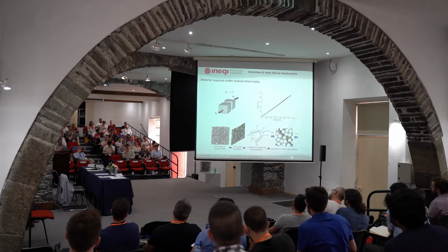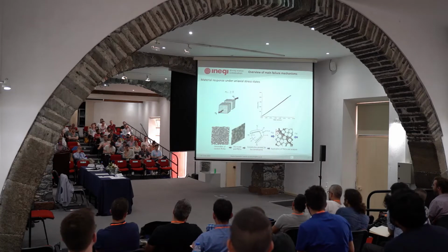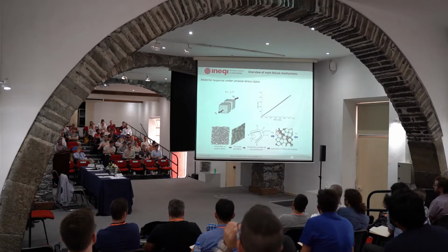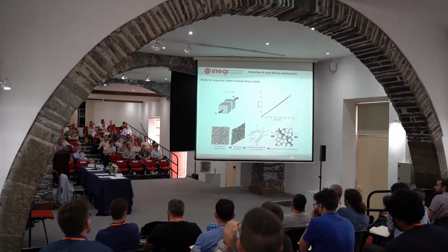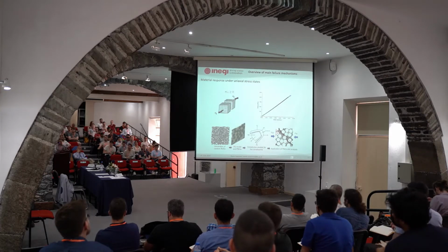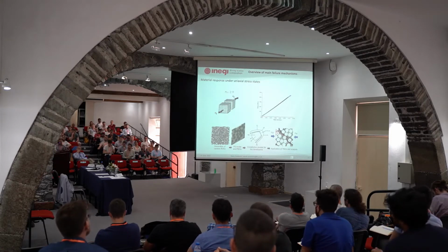So you have a stress-strain relation over there, linear to failure, but if you want to test a composite in longitudinal tension, you'll start loading, and at values of stress or strain close to the failure load you start to hear some acoustic emissions, so individual fibers breaking, and then when you have a completely catastrophic failure, you end up with nothing. So it's very difficult to understand from tests what's going on, at least from these tests, for example, following ASTM standards to get stiffness or strength.